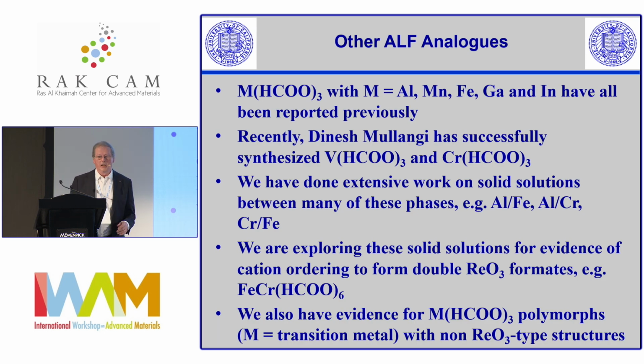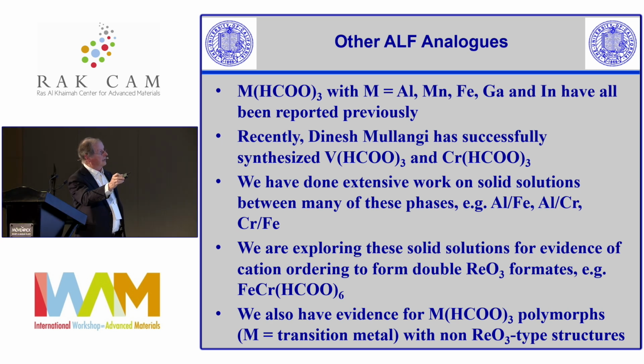Let me just mention one other thing. We've been looking at other ALF analogs, and I mentioned phases with aluminum, manganese, iron, gallium, and indium being made. Dinesh successfully made the vanadium analog and the chromium analog. The chromium analog's a bit tricky because of the kinetics of working with chromium. And we've done extensive work on solid solutions. You just saw a bit of it with the iron aluminum, but we've done a lot on solid solutions to tune adsorption properties and so on.